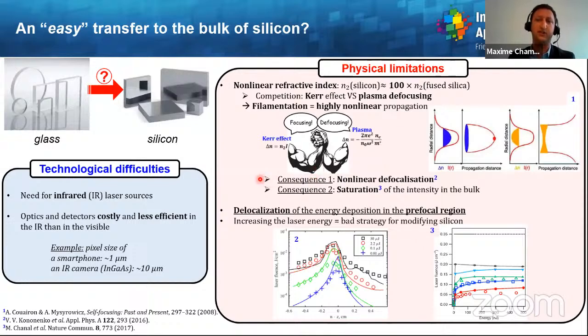And there are two consequences to this. First, as illustrated here, there will be a nonlinear defocalization. Here you can see that the focus is unambiguously shifted upstream towards the laser. The second consequence is a saturation of the intensity inside the bulk of the material, which is illustrated here. When you take those two consequences together, there will be a delocalization of the energy deposition in the prefocal region. As a consequence, one can conclude that increasing the laser energy will be a bad strategy for hoping to modify silicon with ultra-short laser pulses.